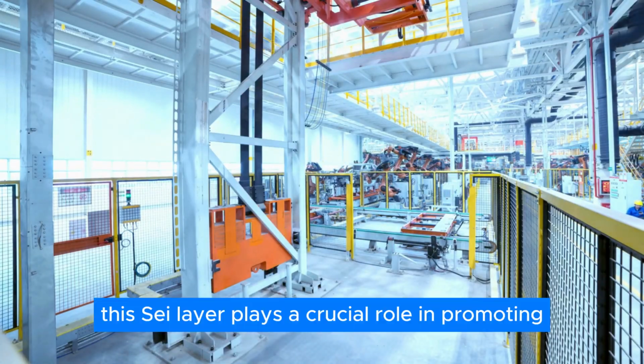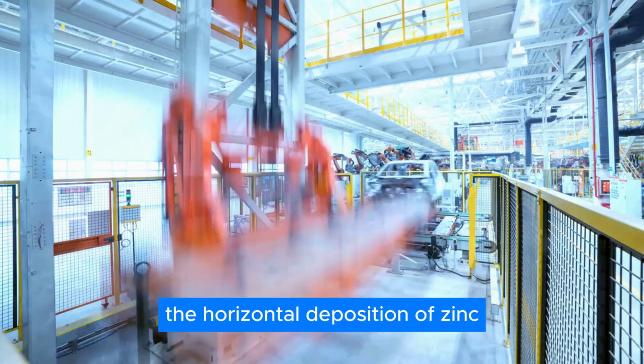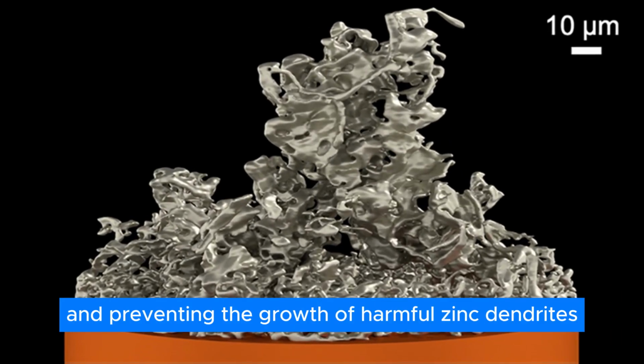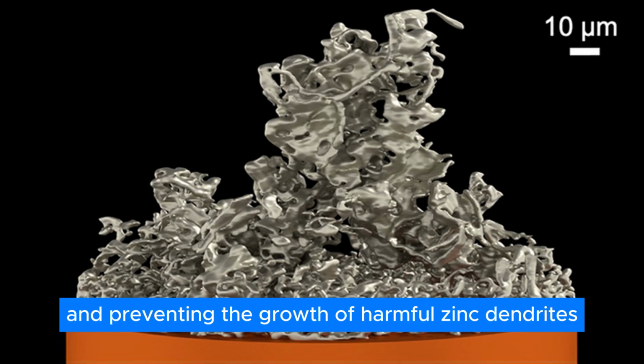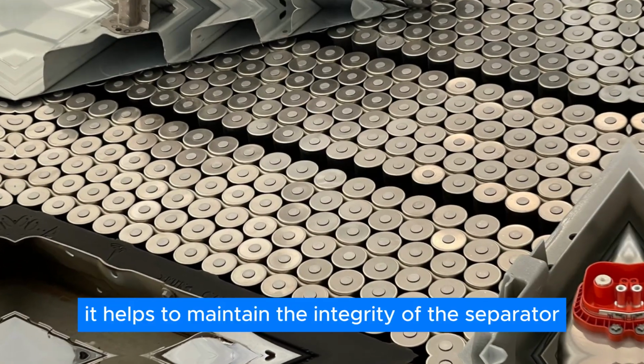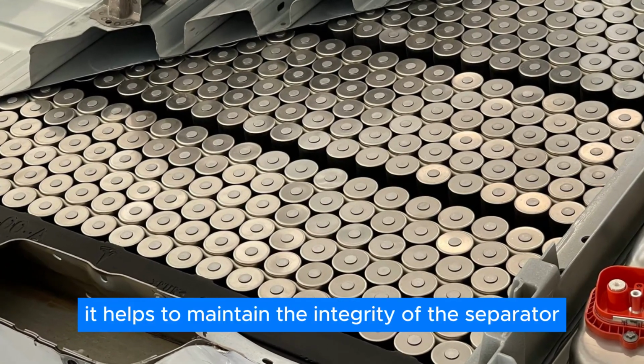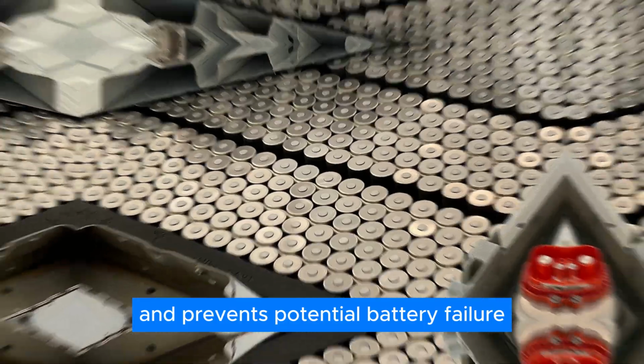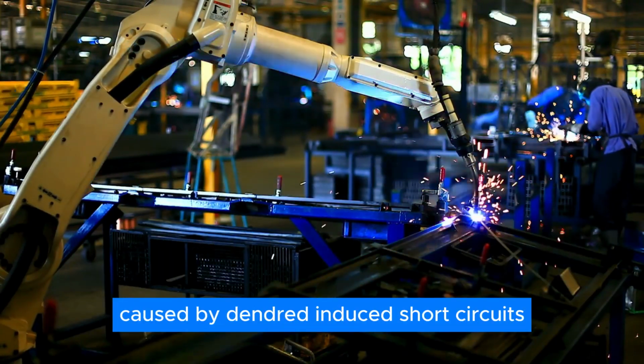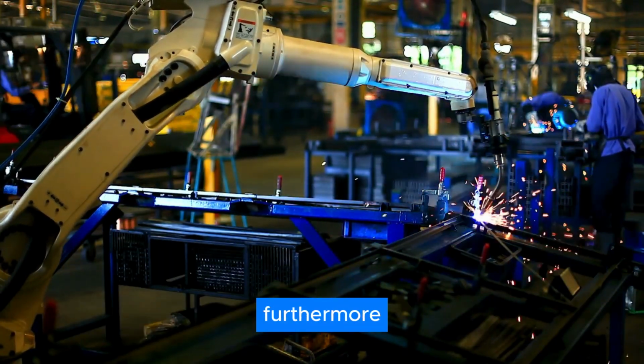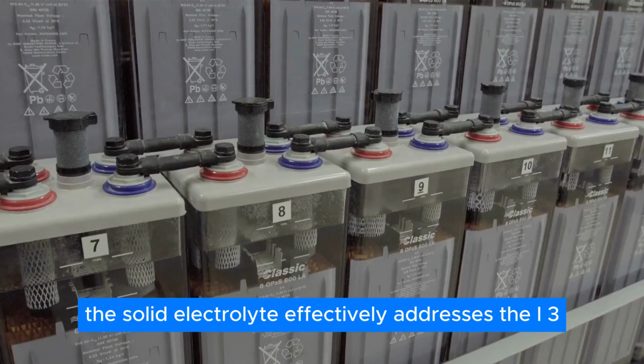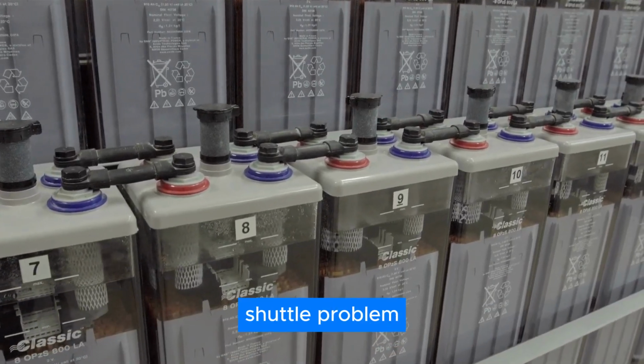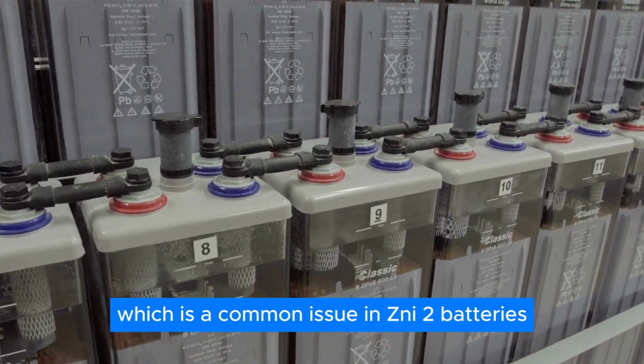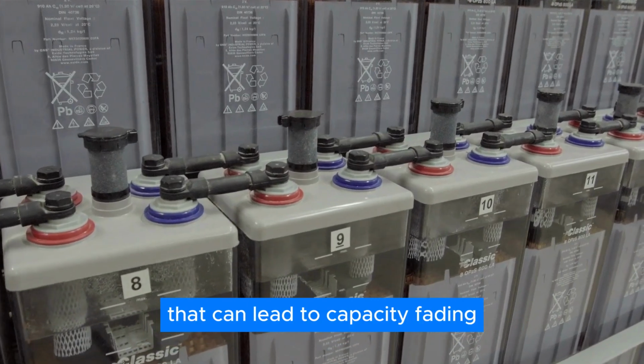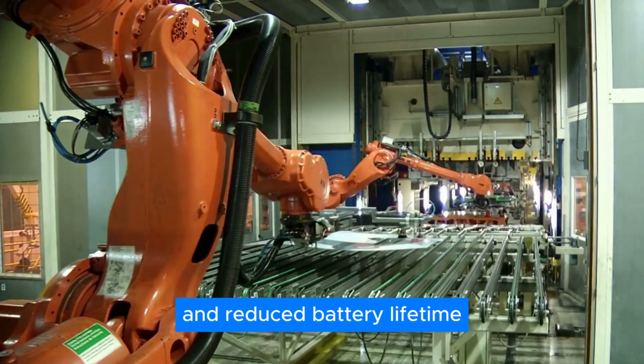This SEI layer plays a crucial role in promoting the horizontal deposition of zinc and preventing the growth of harmful zinc dendrites. By doing so, it helps to maintain the integrity of the separator and prevents potential battery failure caused by dendrite-induced short circuits. Furthermore, the solid electrolyte effectively addresses the I3 shuttle problem, which is a common issue in ZnI2 batteries that can lead to capacity fading and reduced battery lifetime.